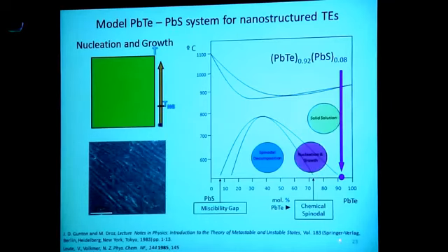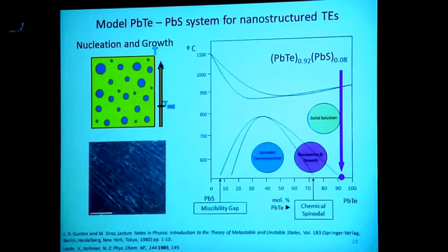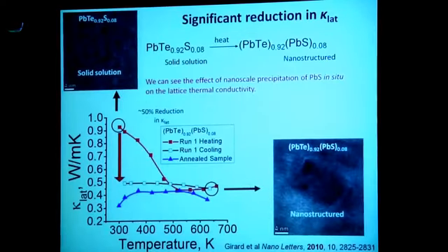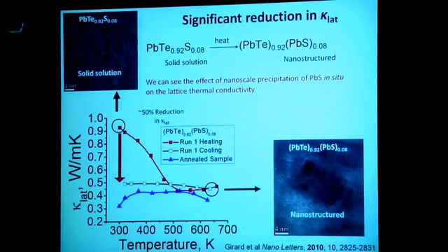So we took that quenched sample and back up, we annealed it. And if you anneal it, it precipitates these things, lead sulfide, all over the structure of the lead telluride. So if you raise the temperature, then you have these nanocrystals spontaneously form all over the place. So now we have the two flavors, the solid solution and the nanostructured material. And so we were able to do the definitive experiment.